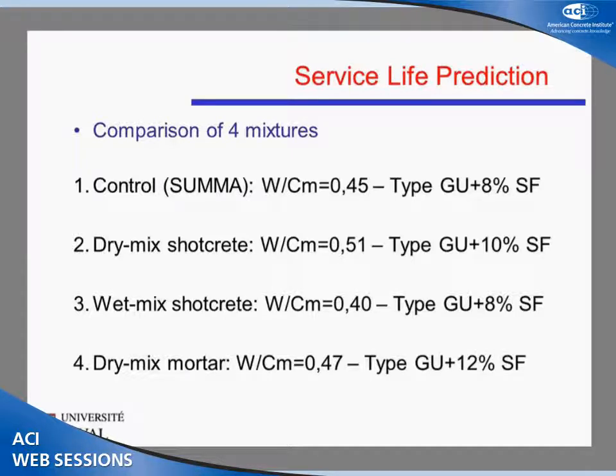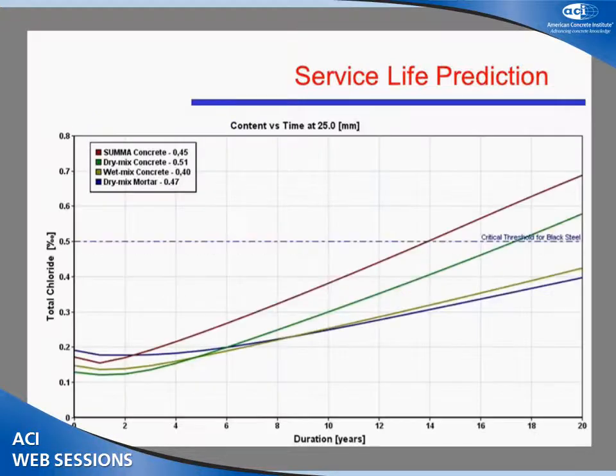The last mix we considered in this specific example is a dry mix mortar, which has a water binder content of 0.47 and a 12% replacement of silica fume with type GU cement. So this is what it looks like once it comes out.